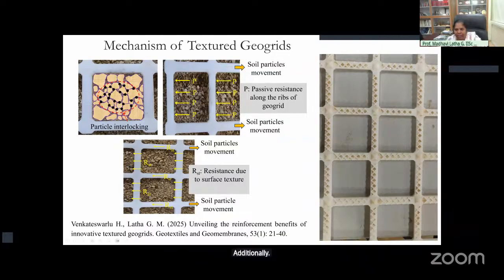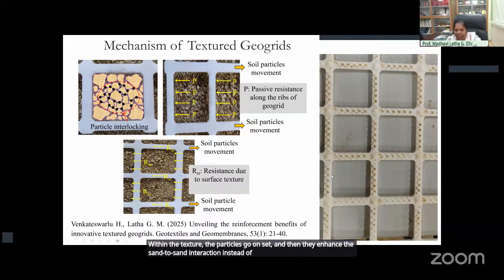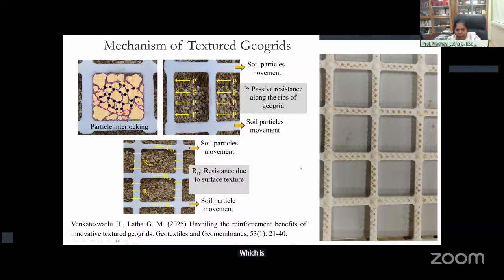Additionally, this is one sample of the exhumed geogrid after the test. Within the texture, the particles sit and then they enhance the sand to sand interaction instead of sand polymer interaction, which is mainly responsible for the increased load carrying capacity and shear resistance.